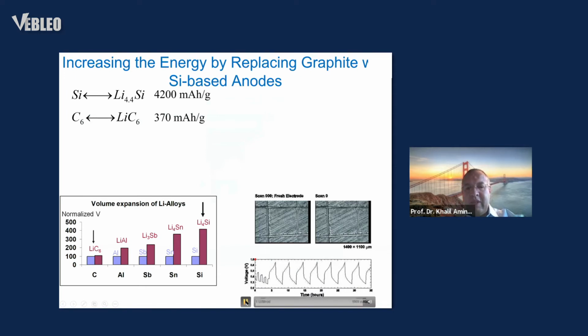This is an area where we did an AFM, where we have a fresh electrode as a comparison and a scanned electrode. So once you start alloying lithium with silicon, you pay attention to this right figure here. Hopefully it's very clear. You will see that the cracking starts happening, and the cracks become very significant once you go to higher charge. See that? So this is initial, the first cycle.